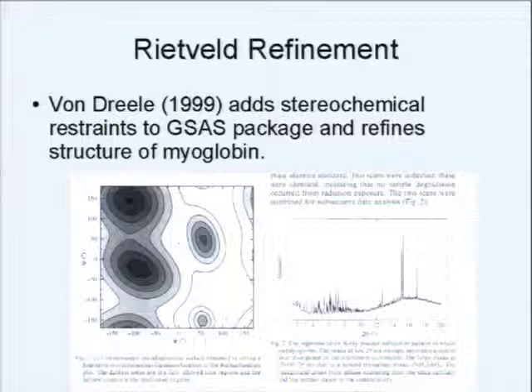One of the aspects is that you get very high quality powder diffraction patterns with extremely sharp diffraction lines — a lot of rich information in the powder diffraction pattern from a protein. And then, in order to get everything to hold together in the refinement, Bob actually invented new kinds of restraints, fitting onto the Ramachandran plot of how the torsion angles along the backbone hold the structure together. When you have an alpha helix, you have particular positions in these torsion angle plots where the torsion angles like to go.